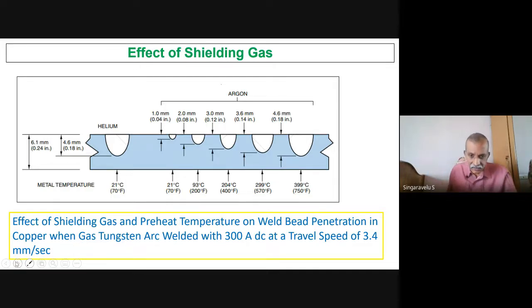Coming to the effect of shielding gas with respect to preheat on the bead or the penetration effect, you can see that with helium, this is the penetration, almost 6 mm thickness, almost 5 mm. You can see that, right? In the case of argon, if you preheat to 400 degrees, then only we can do the same 4.6 mm penetration. That's why we said the effect will be more with helium, or here you have to go with almost 400 degrees to achieve the same penetration, right? And if you reduce the preheat temperature with argon, the penetration comes down. Why? It immediately dissipates the heat. Okay.